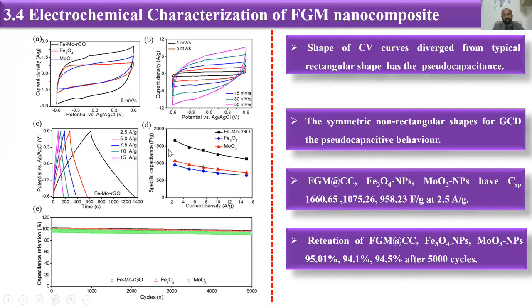Then we have calculated the specific capacitance of our FGM, Fe3O4, and MoO3 nanomaterials for our system, and we have got different values. Then we have cycling retention for the system at about 5,000 cycles, and we have got these types of retentions for our composite, our Fe3O4 and MoO3 materials.